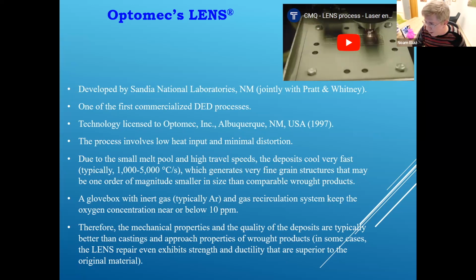The process involves very rapid cooling rates, note, 1,000 to 5,000 degrees per second. It, of course, affects the thermal residual stresses, but also the mechanical behavior. I will touch on it later. You can get very fine grain structures that may be much finer than the comparable wrought alloy. Therefore, for instance, when you do repair with DED, the repaired area sometimes has better mechanical properties than the parent part.